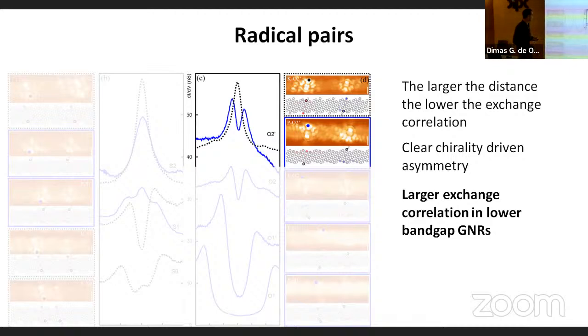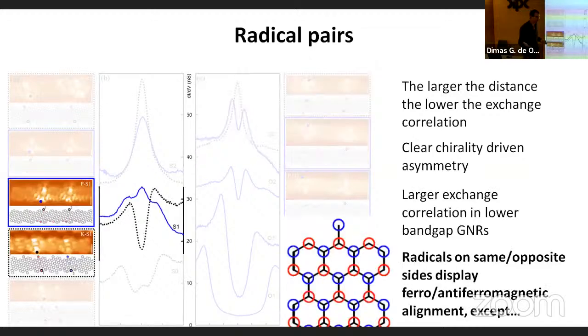And then the last curious thing that we saw is that in general, graphitic structures can be seen as 2 interpenetrated hexagonal lattices. So it's like a bipartite lattice, with 2 hexagonal lattices, let's say red and blue, in which each atom of one lattice only binds to atoms of the opposite lattice. Now, because if you have a chemical bond, you want 2 electrons to be antiferromagnetically aligned. If they're ferromagnetically aligned, you don't bind them. And this means that in general, you assume the spins on one lattice to be the opposite orientation from the spins on the opposite sublattice.